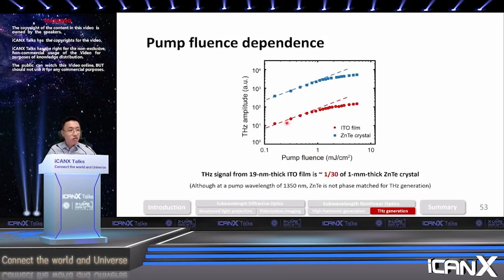The last thing I want to say is that people are most interested in how efficient this is. So we did a direct comparison of the terahertz signal generated from the 19 nanometer ITO film with a zinc telluride crystal with 1 millimeter thickness, which is much thicker than this. We found that this terahertz field amplitude is only roughly 1/30 of that of the zinc telluride crystal with a much larger thickness. Although not as good, it's quite an encouraging signal for us.